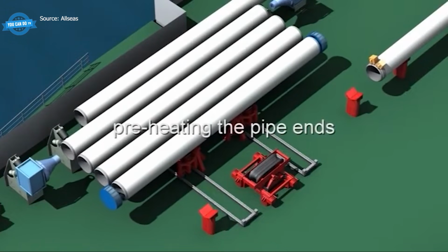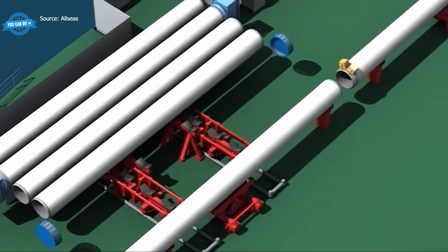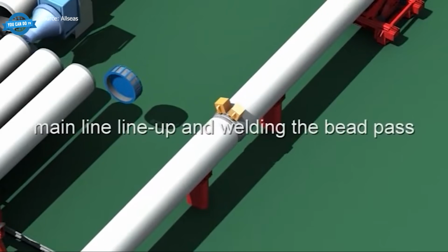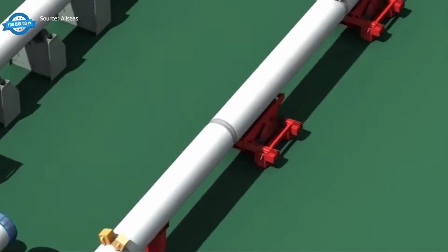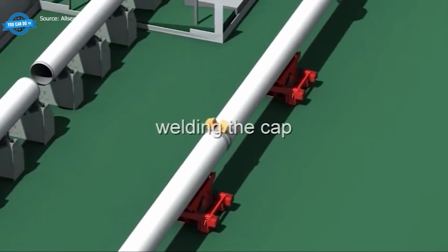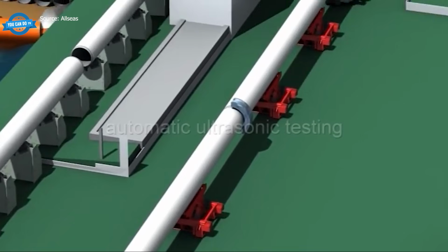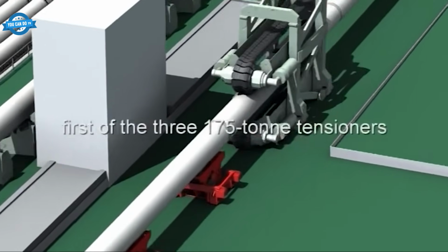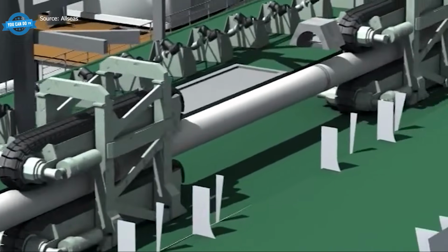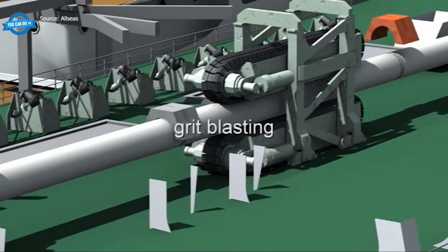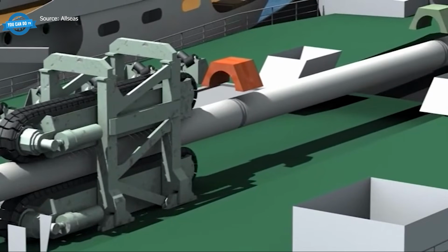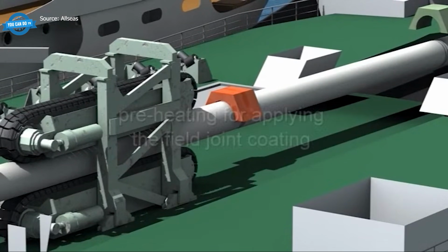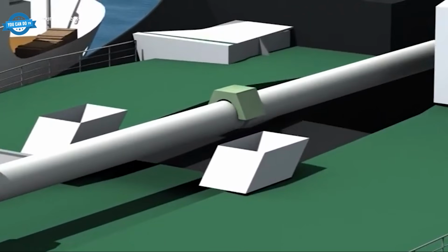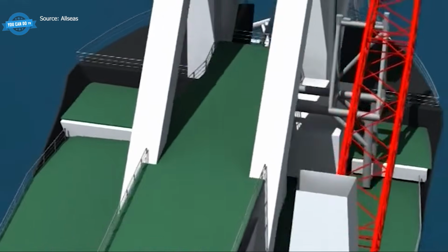Each completed weld passes through automated ultrasonic testing to catch internal defects. The pipe then enters the first of 3 tensioners, each rated at 175 tons, which grip the pipe and control its travel speed along the firing line. Past the tensioners, the weld area is grit blasted and preheated, then sealed with field joint coating to restore corrosion protection over the bare welded zone. The pipe then runs out over the stinger at the stern and descends to the seabed in the classic S-lay curve.